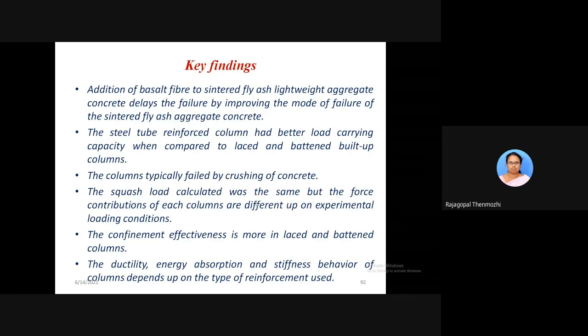So the key findings from this experiment are that the addition of basalt fiber to sintered fly ash lightweight aggregate concrete delays the failure by improving the mode of failure. The steel tube had better load carrying capacity, and the columns typically failed by crushing. The squash load calculated was the same, but the force contributions of each column will be different. And as we are providing lacings and battens, the confinement effectiveness is much more in laced and battened columns. So those columns exhibited a good amount of ductility and energy absorption also.